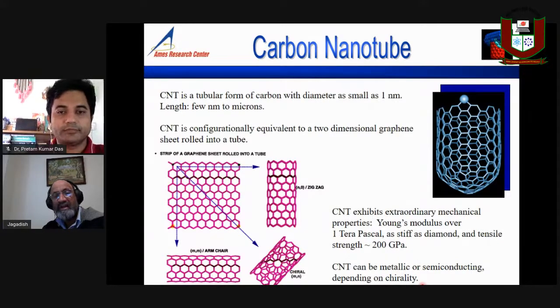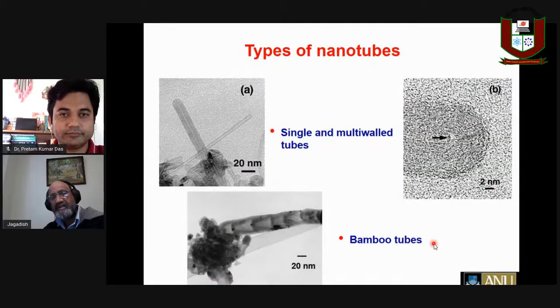And again, their Young's modulus is 1 terapascal, as stiff as diamond, and tensile strength is about 200 gigapascals. So really, they have some very unique properties, these carbon nanotubes. Here are some examples of the carbon nanotubes my colleagues have created at ANU. You can see the electron microscope image of a single-wall carbon nanotube and multi-wall carbon nanotubes here. You can see the close-up of these ones, one carbon atom on top of the other. And you can also get bamboo-shaped carbon nanotubes as well. And all these nanotubes have different properties.